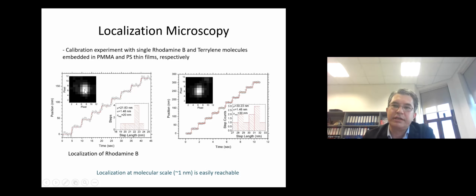Okay, so that's the localization, and if you have bright enough fluorophores and a good enough camera, good enough microscope objective, then you can achieve a localization accuracy much better than the diffraction limit. So we have done this work previously. Here we are localizing some dye molecules and moving the piezo stage step by step, and following the localization together with the piezo motion, you see that we can achieve a localization accuracy of 1.48 nanometers with steps of 30 or 20 nanometers in the piezo stage. So you can localize the molecules much better than the diffraction limit.